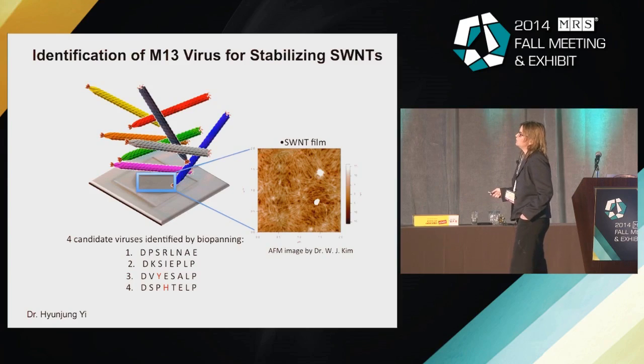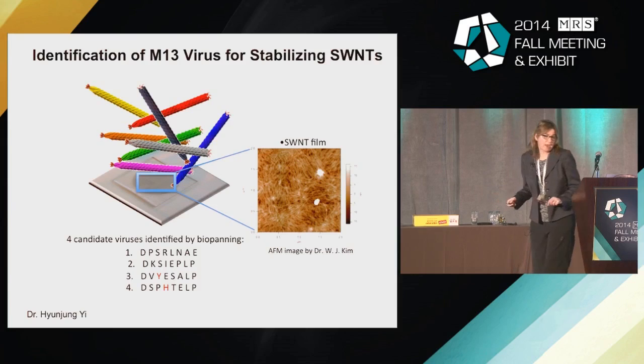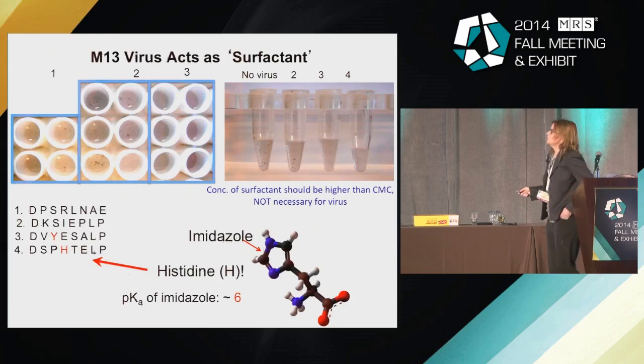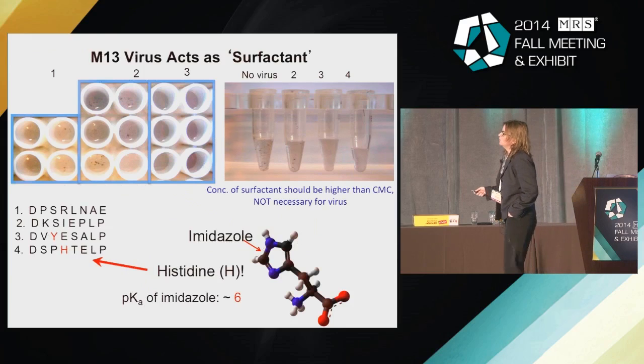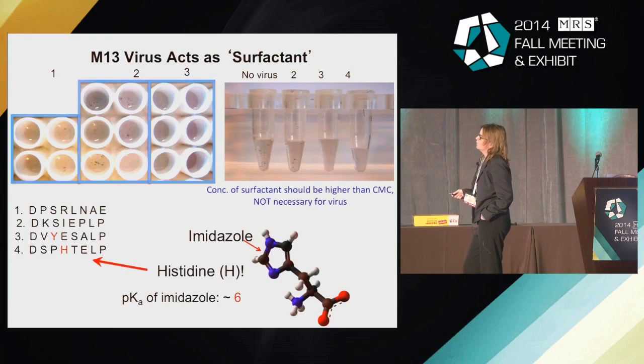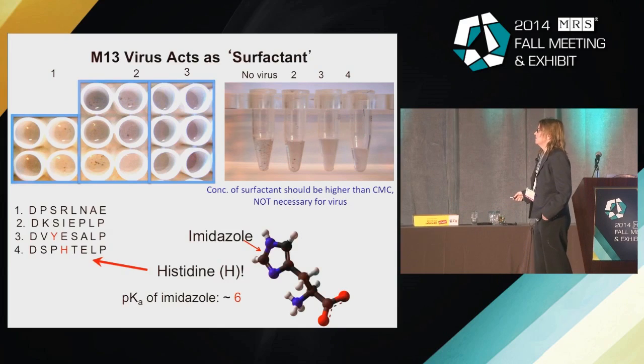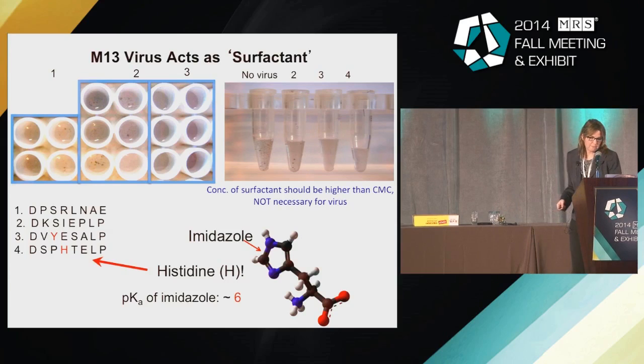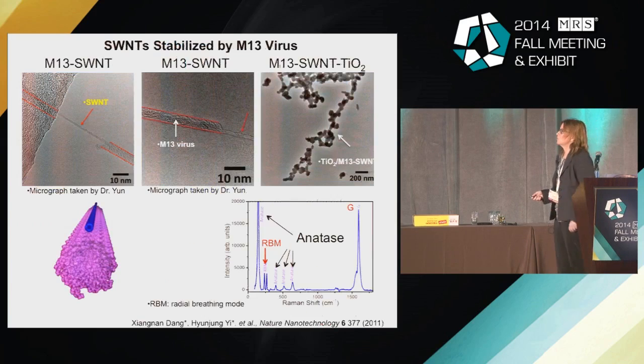Now, what we wanted to do was be able to reduce the surfactant and use the virus as a surfactant. We were able to find virus sequences that could act as a surfactant. So what you're looking at here is dialysis, where we're removing the surfactant and replacing it with different clones of these viruses, and you can find a few viruses that will basically stabilize the CNTs in solution where you don't have clumping. And one of the major things that we were excited about was that it had histidine in it, which was going to be useful for controlling the synthesis and the reaction.